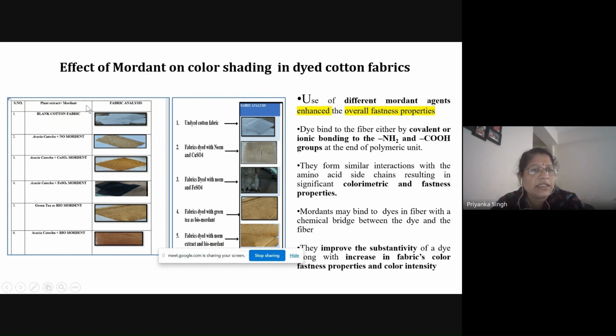In the plain fabrics, we can see the white fabric we have taken, but when we treat it with the acacia, that is only with the babur extract added, we can see a very specific light brown color. But when we add the mordant, copper sulphate, with this acacia, the color varies. This color variation is mainly due to improved binding of this dye with the cotton fiber across the amine and COOH units, and because of that the color variation is observed. In the case of iron sulfate, we observe a blackish color, mainly because of the presence of this mordant.